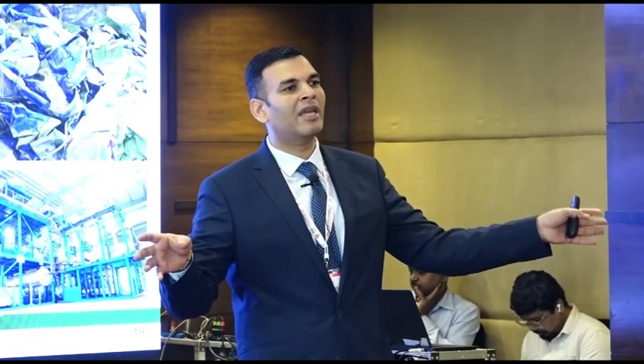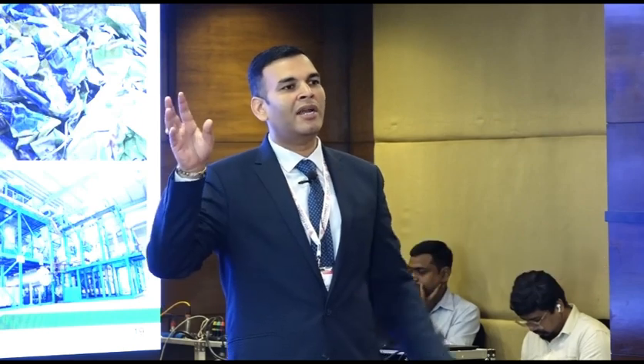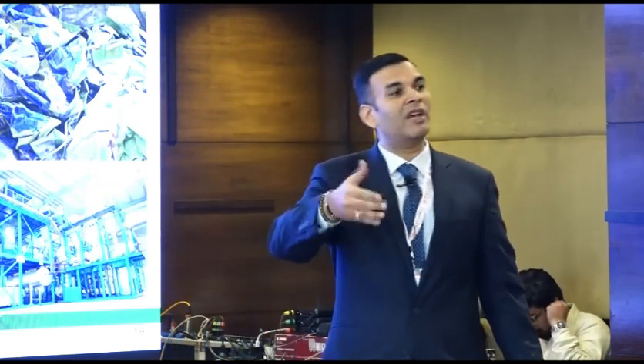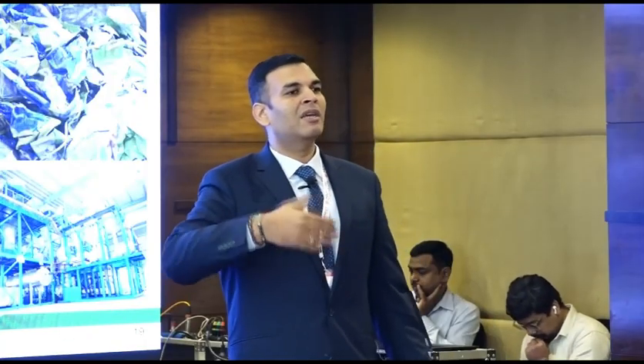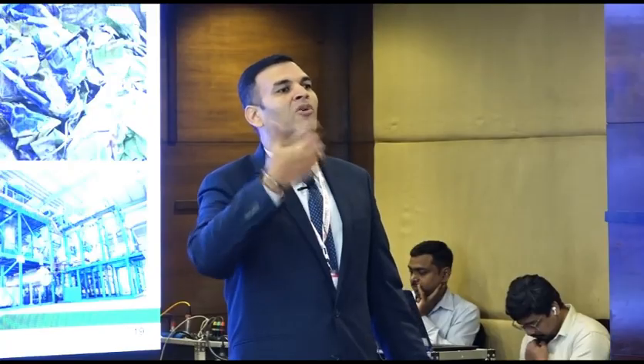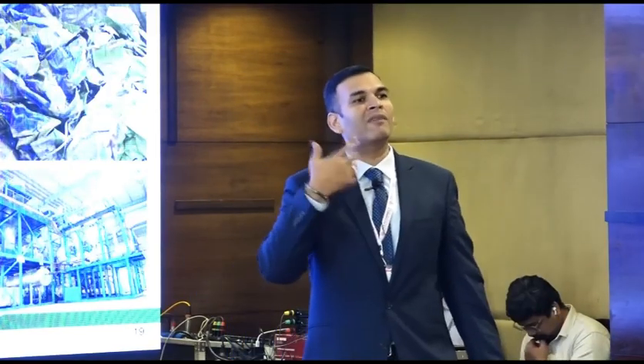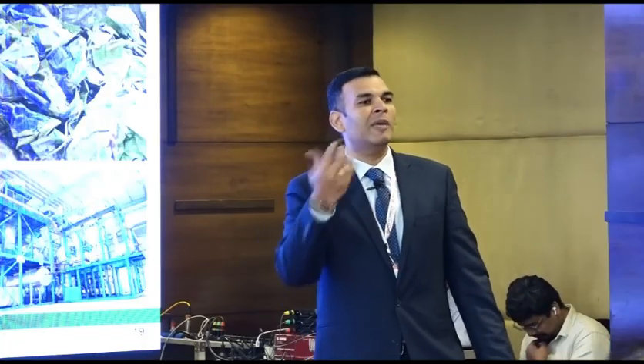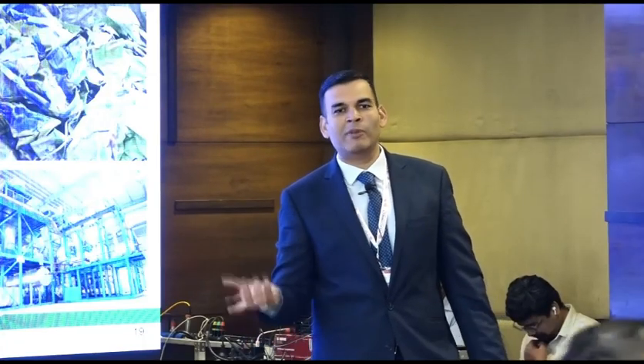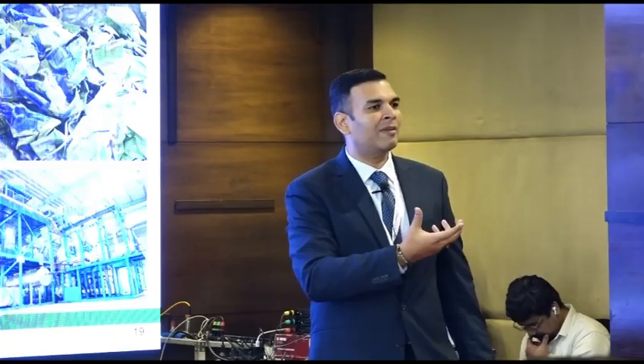Though maleic anhydride has this double bond present, wherein it gives you the functionalities of one end clinging onto the polymer material and the other end which clings onto the filler that we have, and the filler will have another functionality present. Because fillers are inorganic materials, they cannot be tied up on their own, so you'll have to have some kind of functionalization done to filler. Different materials will have different, even if it is glass fiber, PP ka glass fiber is going to be different from PET, because PP's functionality present is going to be different from PET.